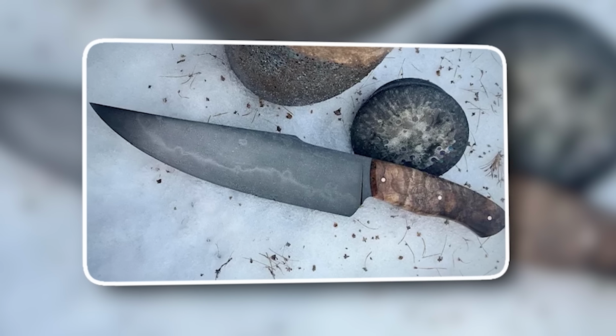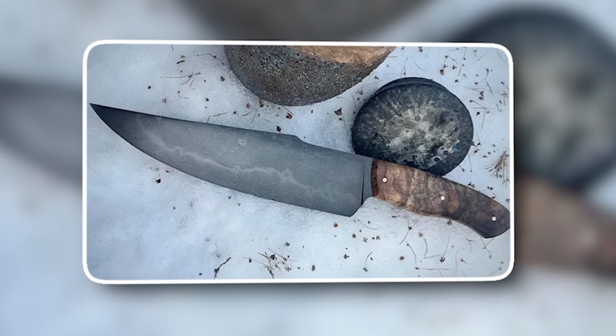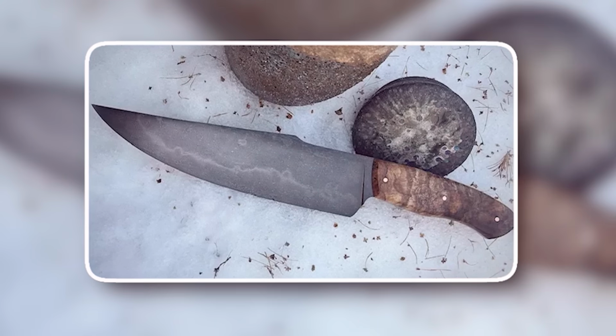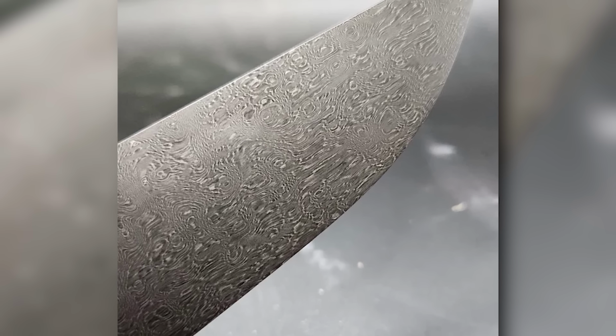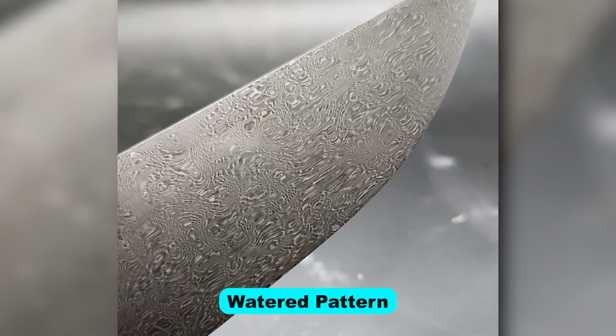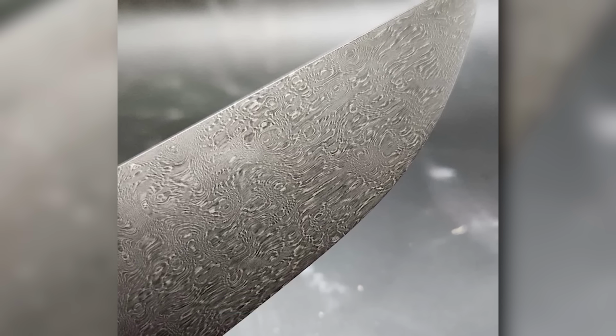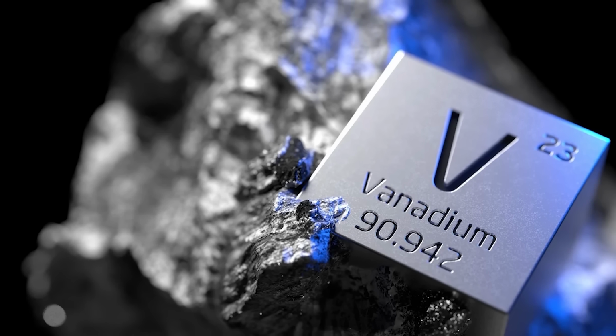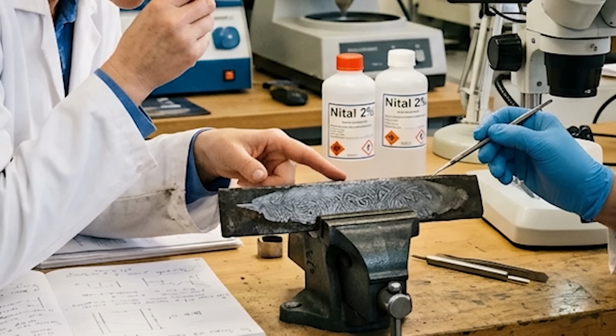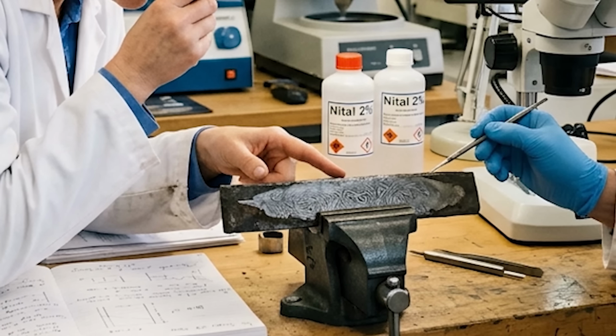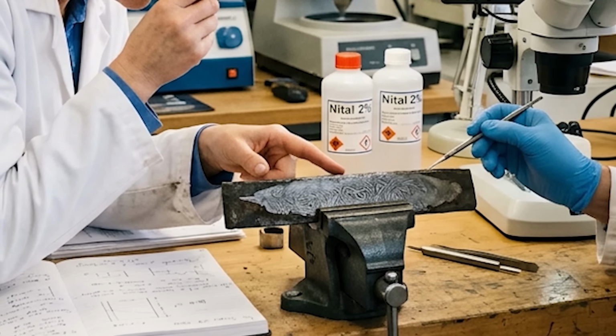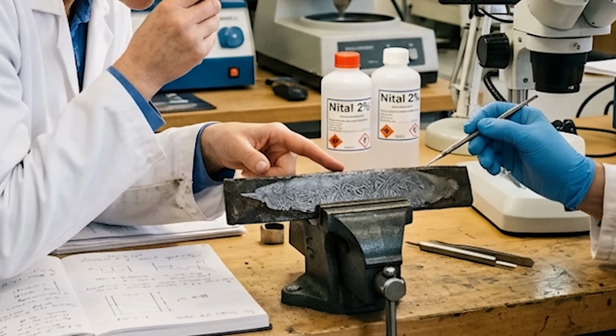The hard bands gave it its edge. The softer bands gave it flexibility. And when the surface was etched, those bands produced the famous watered pattern. But the vanadium was only half the story. Because when another team of scientists looked even closer, what they found inside Wootz steel should not have been possible.